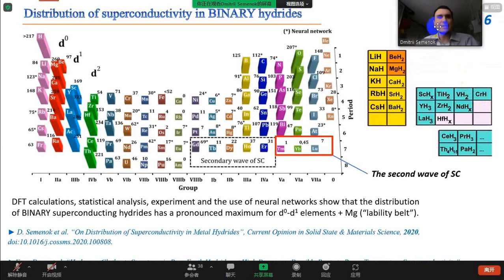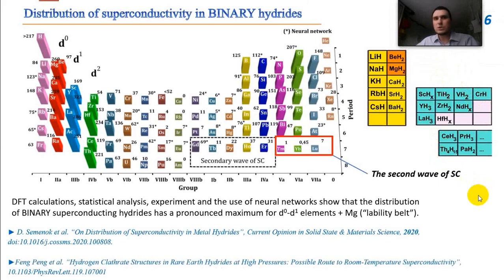After intensive calculations and experimental work, we clarified the distribution of superconductivity in binary hydrides, and it was found that the distribution in the periodic table is actually quite simple. Almost all high temperature superconductors belong to the so-called superconductivity belt. It's a series of elements with d0, d1, and d2 electrons on the outer shell. All other elements do not form superhydrides, or if they do, the superhydrides are magnetic.